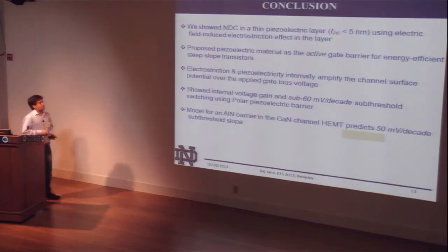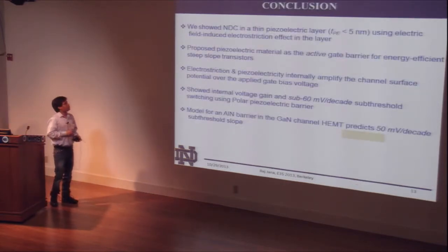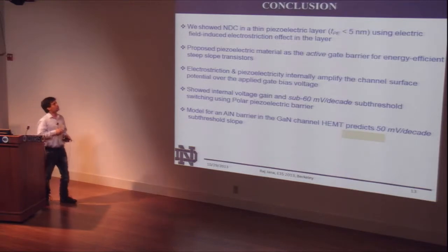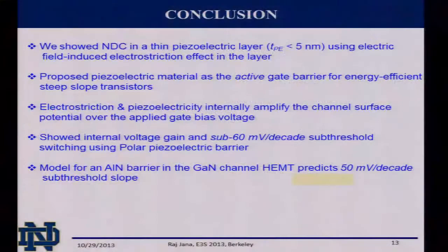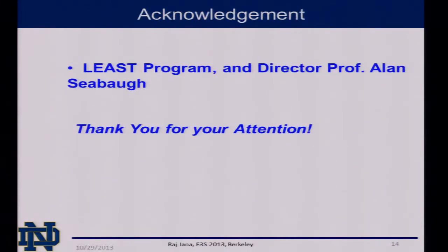So I'm going to conclude my talk. We have clearly shown this NDC, negative differential capacitance effect, in the thin piezoelectric layer just by using the electric field induced electrostriction effect. And that's our motivation to use it as the active gate barrier of the transistor. And here, the electrostriction and piezoelectricity internally amplify the surface potential and also give the associated sub 60 millivolt per decade. And I thank the LEAST program and our director, Professor Alan Seabaugh, and thank you for your attention.